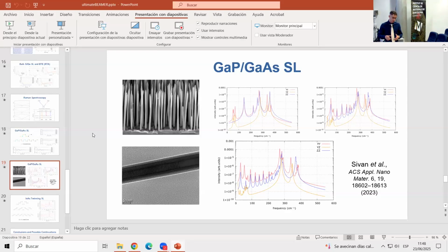When you compute the Raman tensors, you have to study how the system reacts to the incident light, to the variation of the incident light, and to the variation of the electron cloud surrounding the nuclei. So some phonon modes, some acoustic, it is wrong to call them acoustic, some phonon modes are not optically active and you cannot observe them.